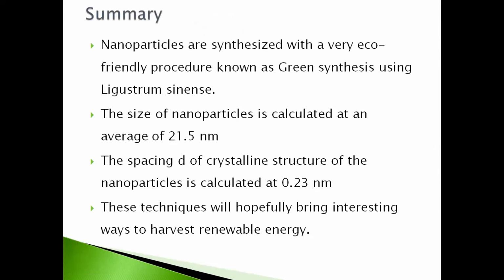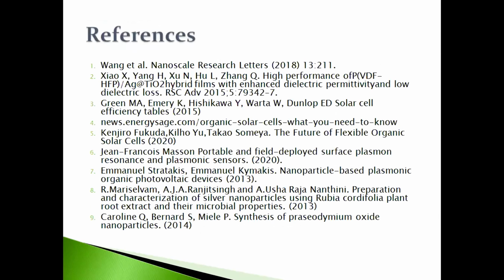Moving on, summarizing my results. So we were very much successful in synthesizing nanoparticles through green synthesis using Ligustrum sinense. Nanoparticle size was calculated to be about 21.5 nanometers through XRD data. And we also calculated the d-spacing using the Bragg equation; the d-spacing of the nanoparticle in the 111 crystalline structure was about 0.23 nanometer. So we hope that this kind of technique of making nanoparticles can be fruitful for harvesting renewable energy for the future. So those are the references of my studies.